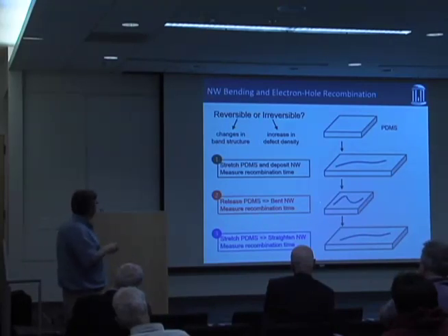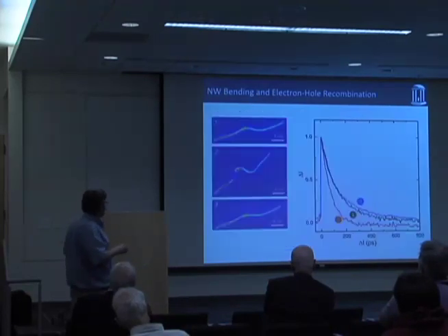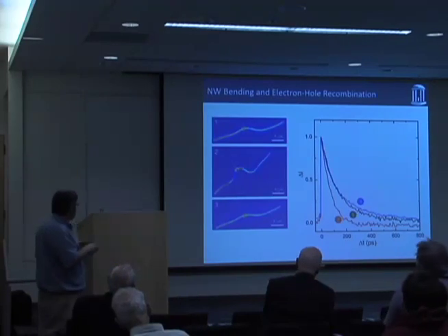Okay, so what we did is we took a piece of PDMS and we stretched it, and then we deposited all our nanowires on it and put that in our microscope and measured the kinetics along the wire. And then we let it go, and all the wires squished up. And then we did the same experiment on the same point and the same wire, and then we stretched it back out, okay, to see if it was reversible. And so here is an example, and this data was taken, what is today? Thursday. So this was done on Tuesday.